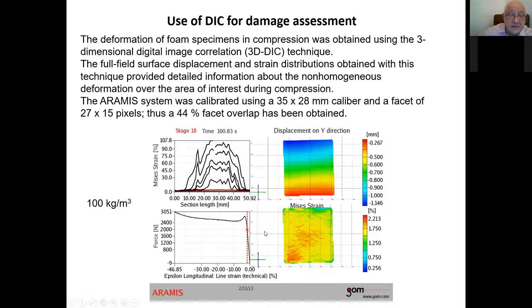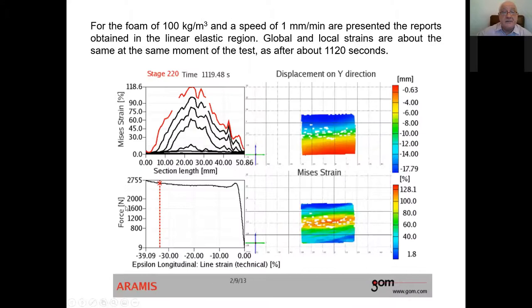As loading is applied, this is compressive loading, you are moving to different locations, and you are able to follow this variation of the strains along the middle line of the specimen loaded in compression. So this is 100 kilograms per cubic meter density, the lowest we have tested. And you can see that in different stages you already have damage of the foam on the surface, and these points are already taken out from the measurements.